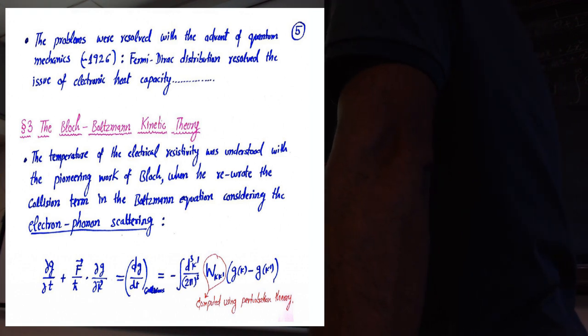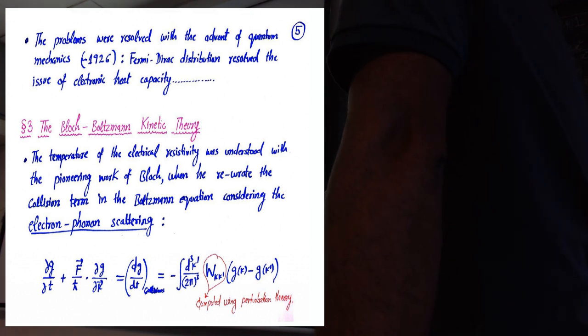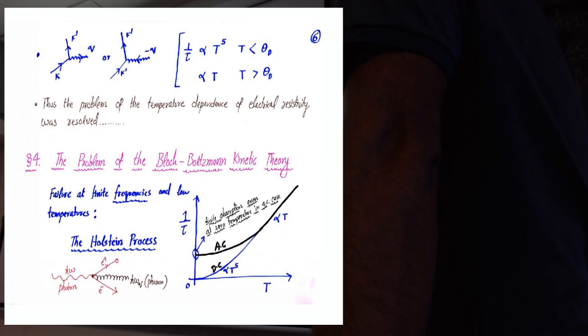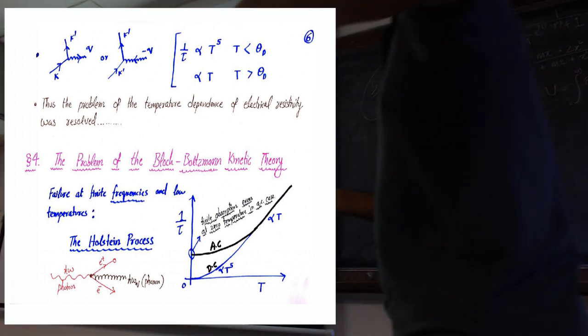Then he solved for the non-equilibrium distribution function, and computed the conductivity. And he obtained these results: at high temperature, resistivity is T linear, and at low temperature, T to the power 5. So this problem which Drude could not solve was solved with the advent of quantum mechanics, because Bloch had a clear understanding that it's not particles striking, it is waves scattering from one quantum state to another quantum state. So he could solve this problem.